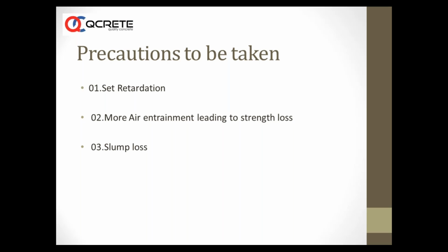Slump loss can also happen if the temperature of cement is more, if the aggregates are not sprinkled or shaded, if there are more fines than earlier, or during trials you used good sand, whereas when producing concrete in large quantities, you might have changed the source of sand where the 150 micron or 75 micron content might have increased. That also contributes to both lesser initial slump and slump loss.